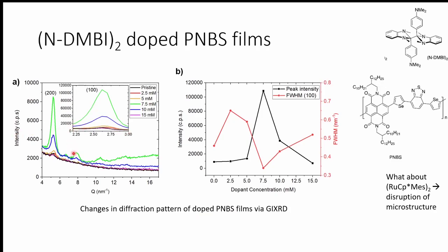What I observed is that at the pristine level or at low doping level, you have broad, low intensity peaks. But as you start increasing the doping to 5 millimolar, your peaks gain intensity and start getting narrower. And then once you hit 7.5, it seems like such a sweet spot that you just get this abrupt sharpening of the peaks, and they increase in intensity. But when you go beyond that, it becomes an overkill and you have too much dopant in there, so it disrupts your morphology.